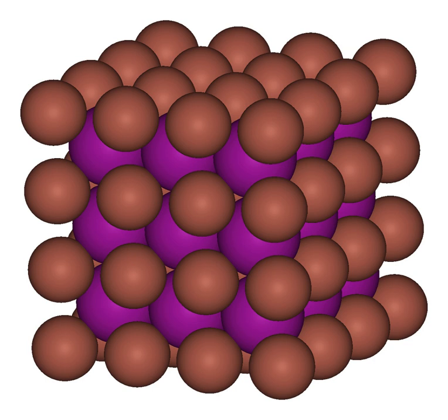Thallium I fluoride. TlF is a white crystalline solid, with a melting point of 322 degrees Celsius. It is readily soluble in water unlike the other Tl(I) halides. The normal room temperature form has a similar structure to alpha PbO, which has a distorted rock salt structure with essentially 5-coordinate thallium. The sixth fluoride ion is at 370 pm.